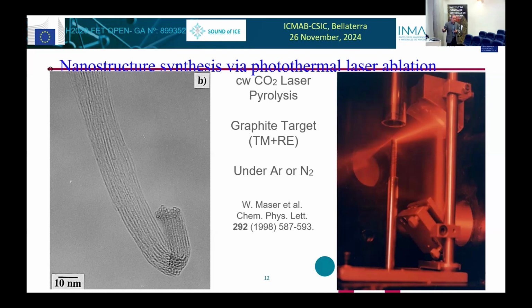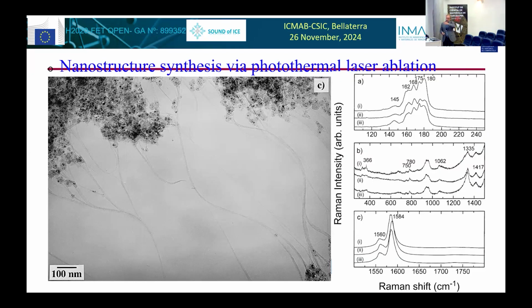We did this many years ago. I was much younger at that time. And this is what it looks like. When you look at TEM, you can see that the nanotubes stem from somewhere, a point, as if they grew from a nucleation center. And this has been identified with a carbide formation where the metal elements are of the transition element and the rare earth. And so I think that they grow from this as a nucleation center. And from there, the nanotube starts growing as a single wall nanotube, which is not easy to attain.